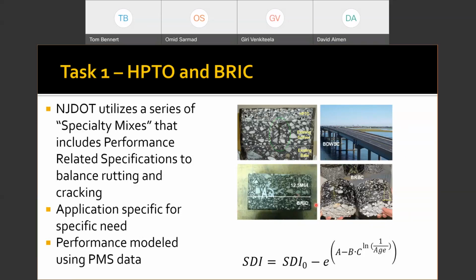We also have what we call a bottom-rich intermediate course. This is for the bottom of our asphalt overlays over concrete. And then we also have developed a bituminous-rich base course. And this is used when we're trying to produce what we call perpetual pavements, where we're designing and constructing a pavement so it does not crack from the bottom up. The only distresses that occur are on the surface, which can be milled off and then replaced. So in essence, we have a long-lasting structure in place.